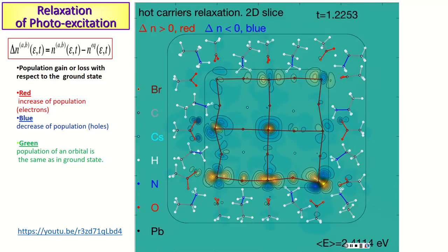It's not ideal. Ideally, most of the density should be only in the center. Here, there are some, I wouldn't say traps, but similar trap states where more density is on the corners rather than in the center. But the good sign is that the amount of density on ligands is vanishing. So indeed, a substantial majority, like 99% of the density of both electrons and holes, is on the core of the structure, on the perovskite scaffold, and it is expected to be emissive.